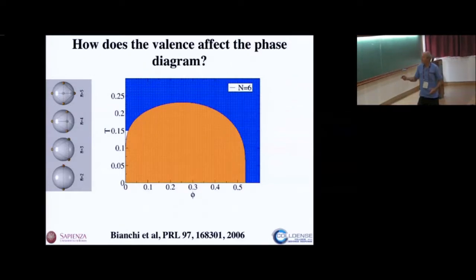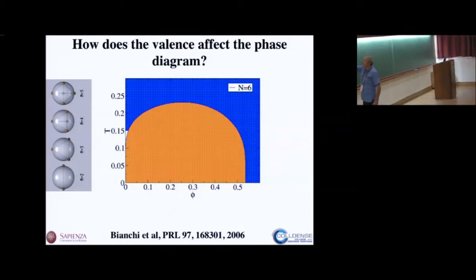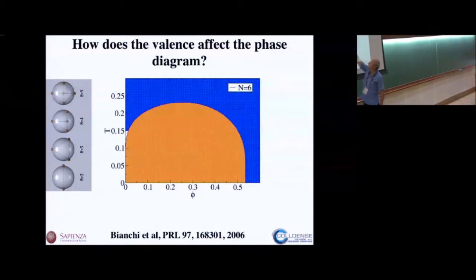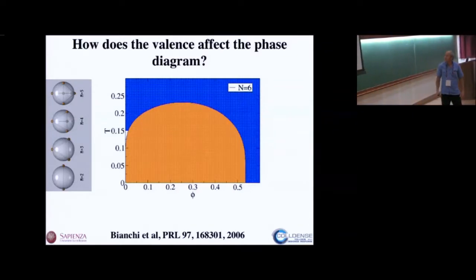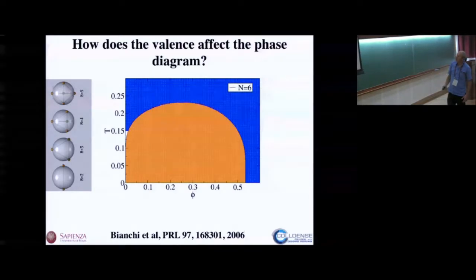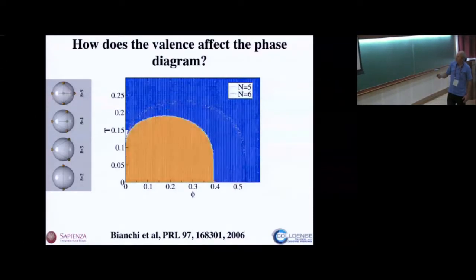Nothing really changes. You see the density of the liquid coexisting with the gas is rather high. 50% of the volume is occupied with particles. So it's already a dense state, and there is not much we can do here. But we can go to lower values, from 6 to 5. You see already a significant decrease. You see that the critical temperature goes down, the critical density goes down, and you see that the density of the liquid coexisting with the gas shifts to the left.